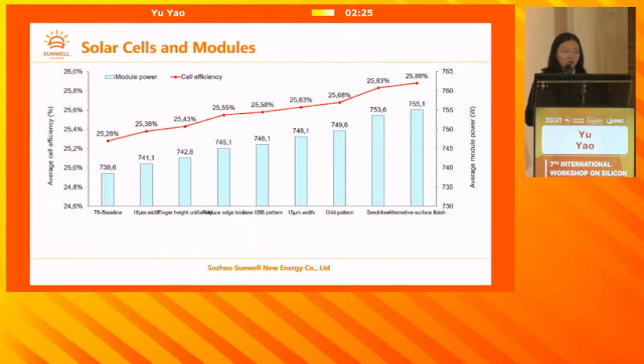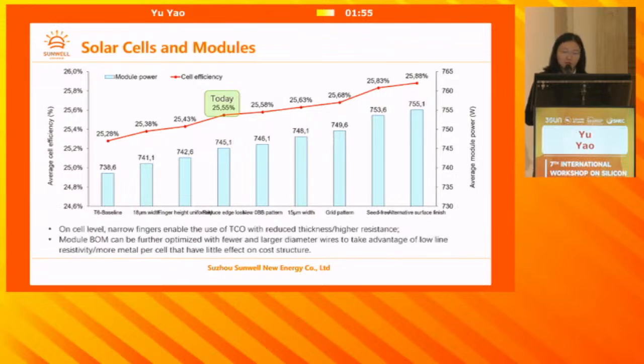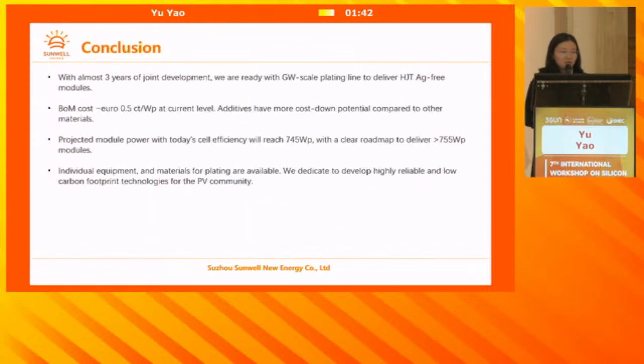And so now we are at a level where the efficiency today is 25.55%, small scale, and this we have done by using almost full area ITO, so the backside is not the standard pocket edge exclusion, and thereby we can increase the current to more than 40.4 milliamp per centimeter squared. And we have also a clear roadmap to achieve more than 755 watt peak in production. And this will translate to 24.4% module efficiency. So with that, I conclude the talk.